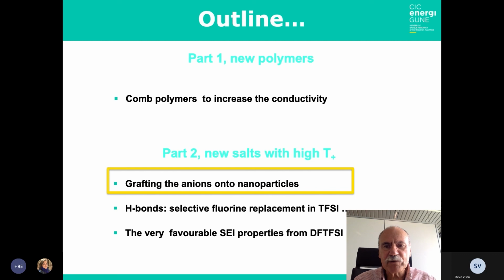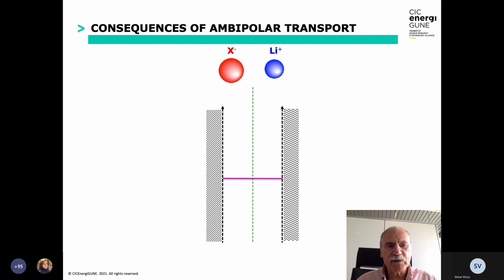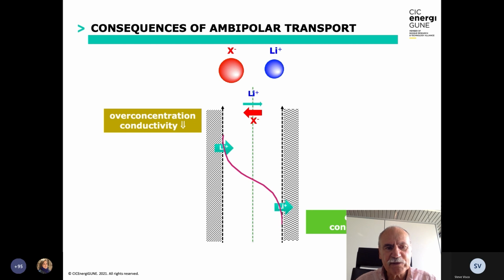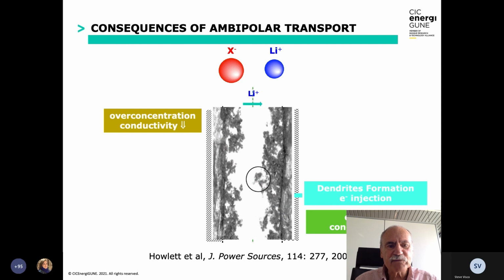As I said, the transport number is a problem because you have got in polymer electrolyte the dual motion of the anions and lithium, and the anion move 2 times faster than the lithium, so the transport number is close to 0.2, 0.3. So what happens, because your electrodes are only using lithium at the interface, exchanging lithium at the interface, you are going to build a concentration gradient of your salt in your battery when you operate it, and this concentration gradient grows until you have got overconcentration and conductivity drops on one electrode, and you have got depletion of salt on the other electrode, and your conductivity drop also. And even worse, what you're doing when you have got concentration gradient and depletion of salt at the interface is the possibility of dendrites growing.